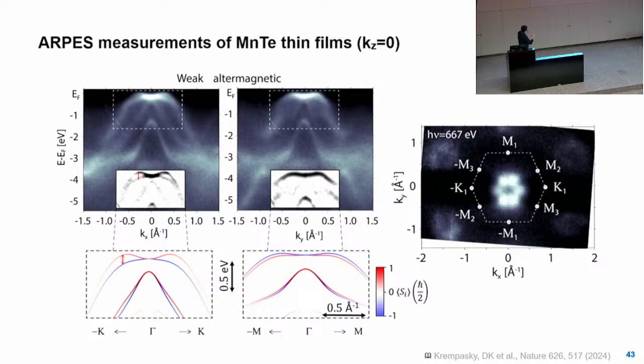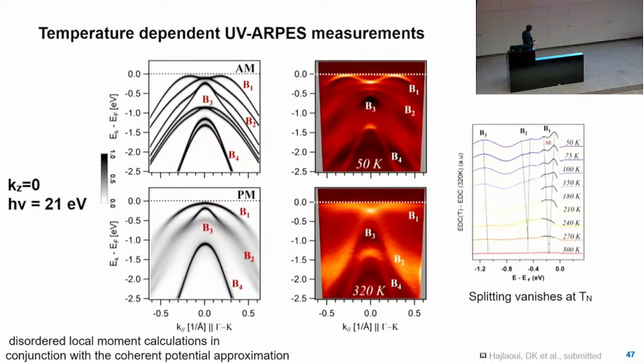Then, of course, we had to do many more control experiments to prove that this is really true. For example, we had to study the temperature dependence. All of this, what I told you, relies on the magnetic order. So when the magnetic order is gone, when you heat the material above its transition temperature, then also the splitting must vanish. So we tracked the splitting, how it evolves with temperature, and it vanishes exactly, or more or less exactly, where the Néel temperature of the material is from other measurements.